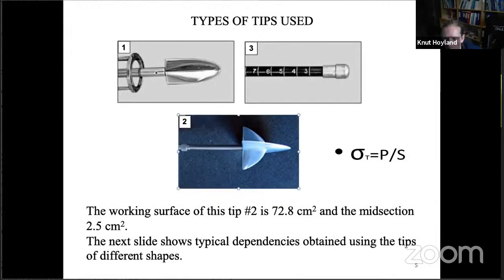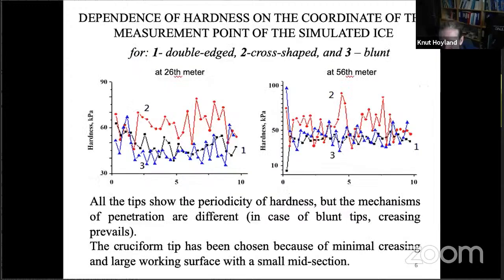Here you can see three tips originally used for the measurement: double-edged, cross-shaped, and the blunt. Here you can see measured dependencies from the tip's type at two different measurement points. What's interesting is that a different penetration mechanism could be seen depending on the tip's form.